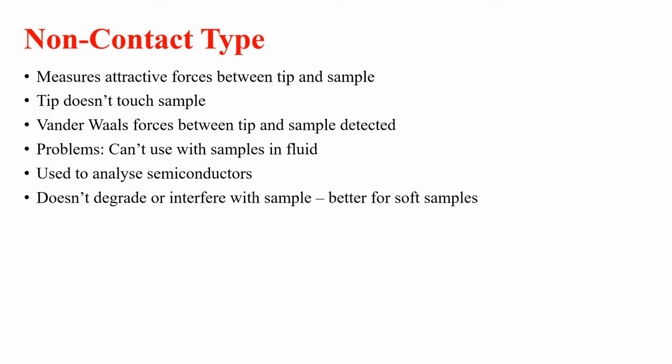So let's see the non-contact type. In non-contact type, the tip of the cantilever does not make direct contact with the sample surface. Instead, the cantilever is oscillated either at resonant frequency or just above it, with amplitude modulation. So these van der Waals forces, which are strongest from 1 nanometer to 10 nanometers above the surface, act to decrease the resonance frequency of the cantilever.